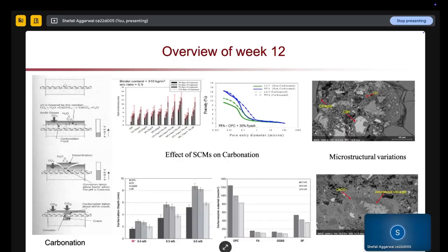Here if you see, at a lower water to binder ratio, the carbonation depth is low. At higher water to binder ratio, your carbonation depth is higher, and this effect will depend on how dense your system is, or how much hydroxide your system has. So this is a microstructure variation. This is uncarbonated, and then this is carbonated. So in uncarbonated you have hydroxide, and in carbonated you have calcium carbonate formation.